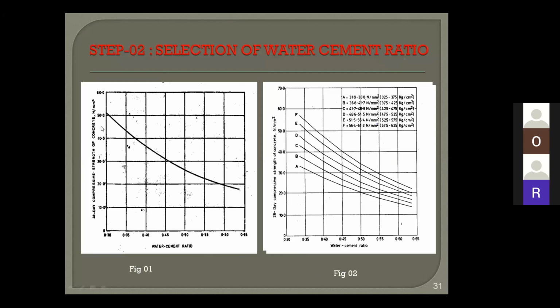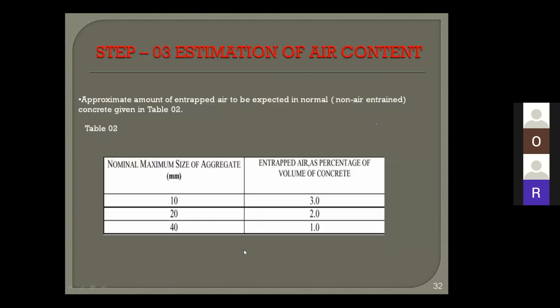These are the 28 days strength results, and this is the water cement ratio. The maximum water cement ratio we have to use is 0.45. Now we have the target strength 42, and we have to plot. We come across at 42, and this is the point we get here. After that, we go down so that we get the water cement ratio we can use. Here we are getting 0.38. We just have to fix the water cement ratio at 0.38.